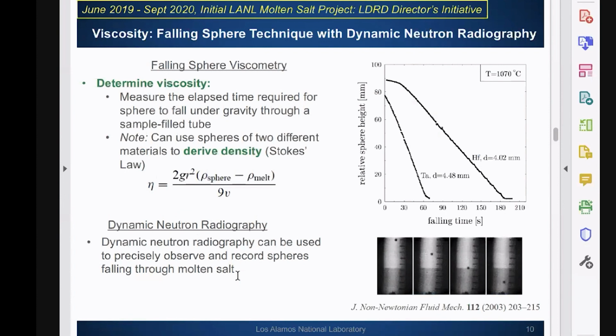Just a quick summary here of the viscosity. Same idea using neutron beam, but now we're blending it with falling sphere. We're just using the neutrons to visualize that. Just as a side note, if I'm being totally honest, we initially started out wanting to do viscosity first and then discovered some issues with sphere contrast. And so rather than trying to derive density from viscosity, we ended up pivoting completely to the dilatometer that I showed you, or neutron dilatometry that I showed you, and then did a couple of measurements of viscosity.